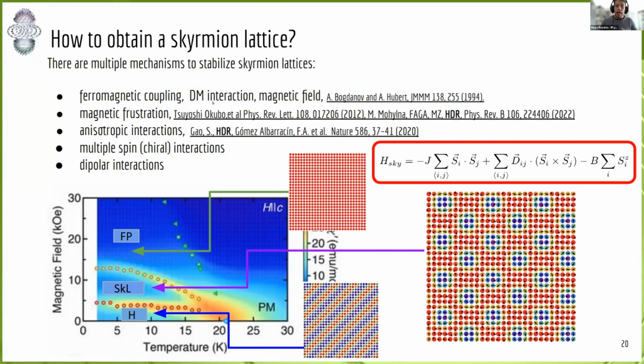But other possibilities correspond, for example, to magnetic frustration, competing interaction, anisotropic interaction, multiple spin chiral interaction and dipolar. But the idea is to go into detail in this phase diagram. This is a typical phase diagram: temperature, magnetic field, with different phases at low temperature. H corresponds to the helical state with the typical one-dimensional arrangement of magnetic moments here. High field here, fully polarized regime.